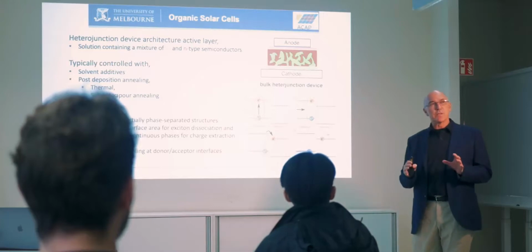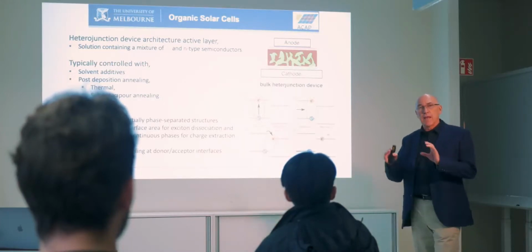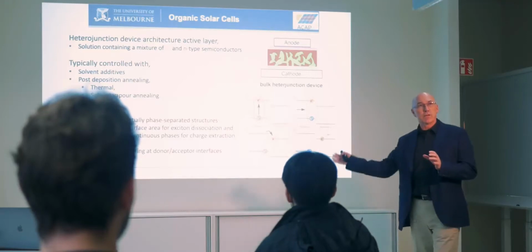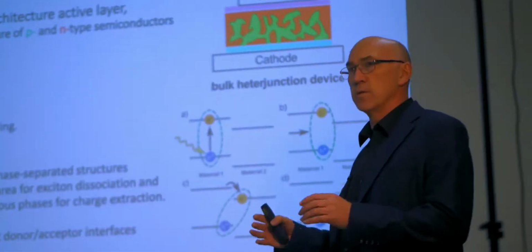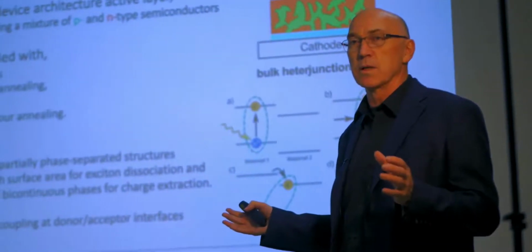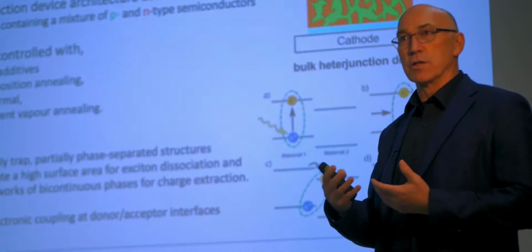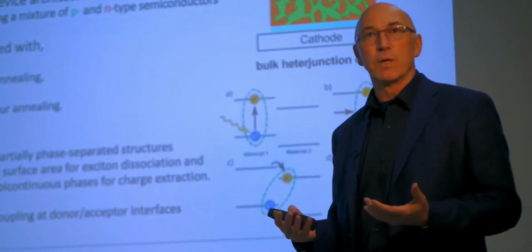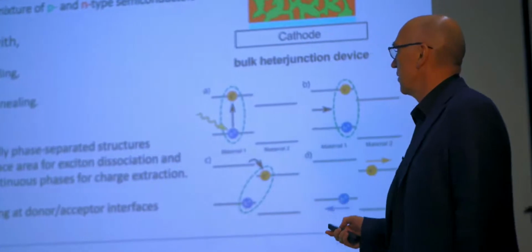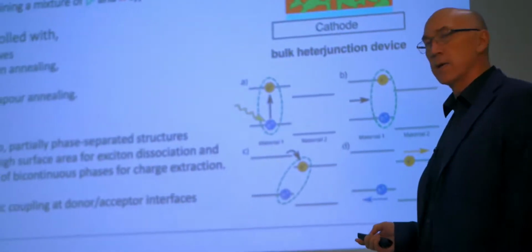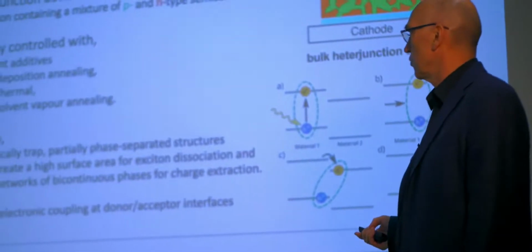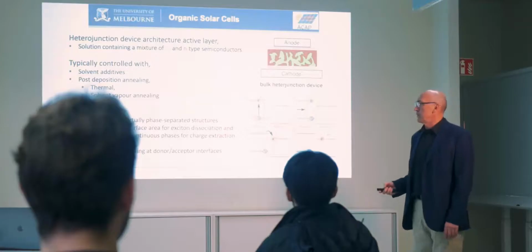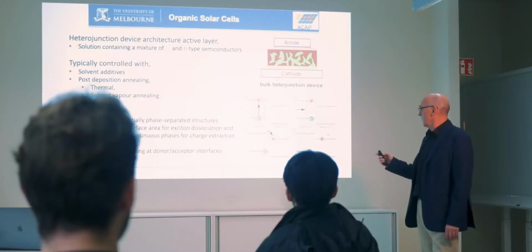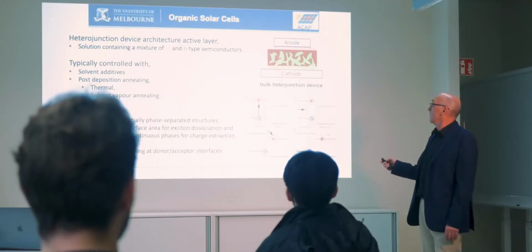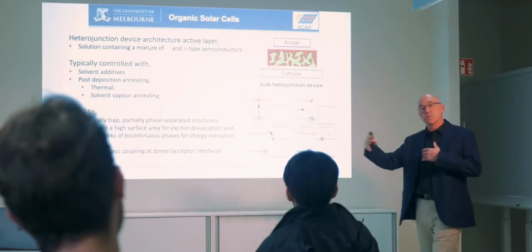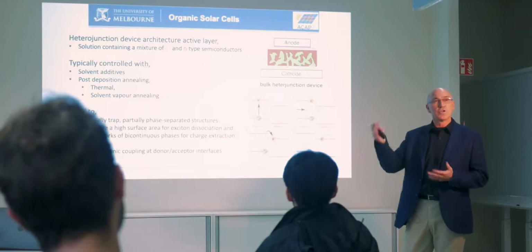The trouble is, in doing this, what we're actually doing is kinetically trapping a structure which can then later on continue to evolve. If we over-anneal it, we get too big domains and the device doesn't work. In operation, the structure can continue to change and therefore we can lose the efficiency of the solar cell. So it's this kinetic trapping that we want to look at and see whether we can change how we structure that. And of course, in doing this, we also want a network of bicontinuous phases. We want to be able to get the charges out of either the P-type phase or the N-type phase. So we need continuous pathways for the positive or the negative charges to get to the electrodes.